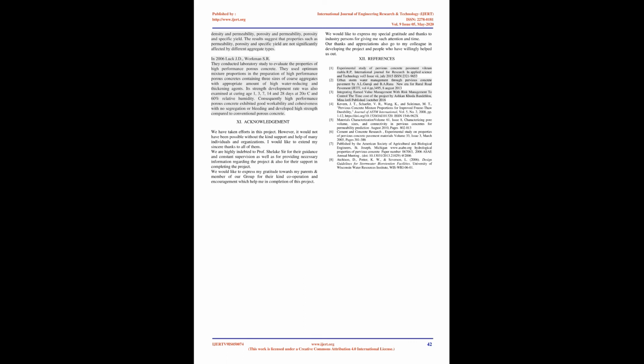In 2006, Luck J.D. and Workman S.R. conducted a laboratory study to evaluate the properties of high-performance porous concrete. They used optimum mixture proportions in the preparation of high-performance porous concretes containing 3 sizes of coarse aggregates with an appropriate amount of high water-reducing and thickening agents. Its strength development rate was also examined at curing ages of 1, 3, 7, 14, and 28 days at 20 °C and 60% relative humidity. Consequently, high-performance porous concrete exhibited good workability and cohesiveness with no segregation or bleeding and developed high strength compared to conventional porous concrete.